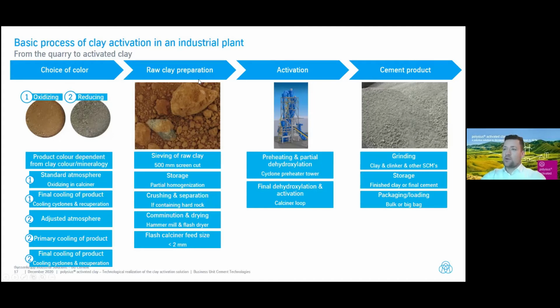When starting now with the raw clay preparation, we are typically sieving the clay. We are having, in some cases, a partial homogenization. So this is depending on the clay deposit at the end. We are separating hard rocks if available or if contained. And then afterwards, we are feeding a hammer deagglomerator with this clay. We are deagglomerating the clay to below 2 millimeters. Afterwards, we are feeding our preheater system, and then we are giving it into the activator unit. I will show you a flow sheet on the next slide.